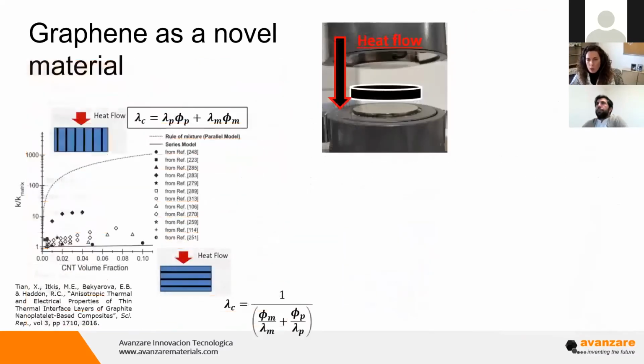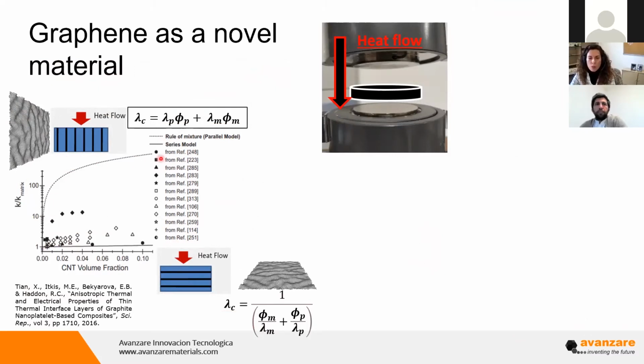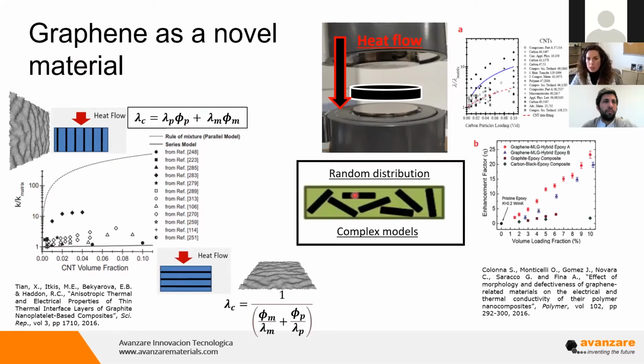So once we have seen this, if we go to modeling and to some theory, if we could orient all our layers of graphene in a direction parallel to the heat flow, this could be really efficient and the movement of heat should be very high. The thermal conductivity should be very high. In the other case, if we put them in the other direction, the efficiency in moving the heat is going to be extremely low. What is happening in reality is that the distribution of the nanoparticles inside the matrix is random, and it's necessary to use complex models, and also the results are usually in the middle, both for experiments and for simulation.